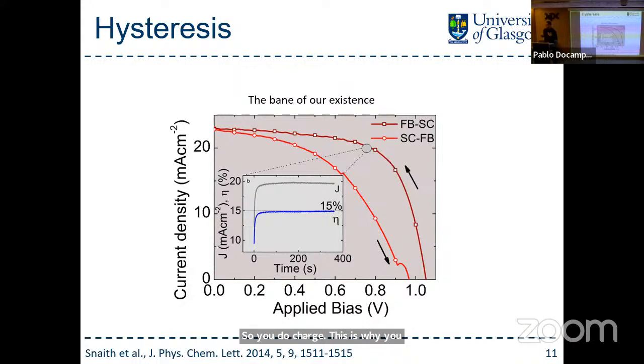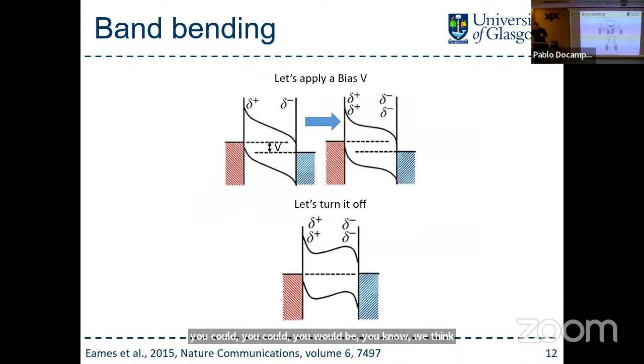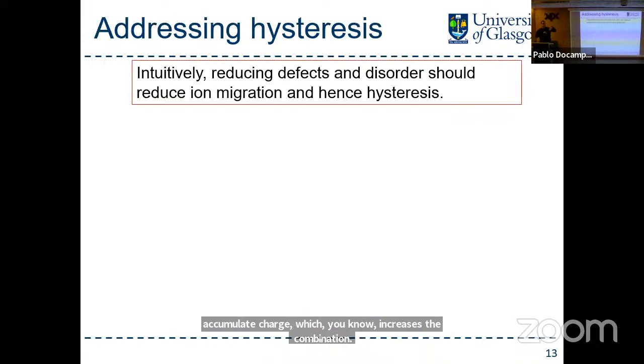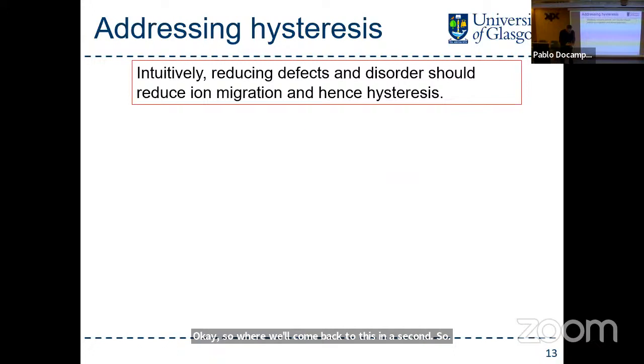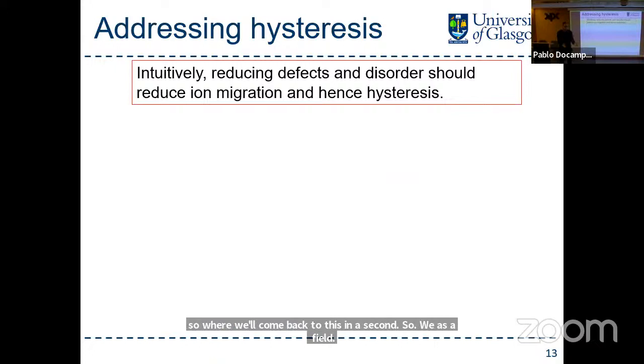So we think of them as not great. We don't want to have them. And this is a bit of explanation of what happened here. Basically, when we first applied the field, we moved the ions to the interfaces, which bends the bands. When we turn the field off, the ions remain in place. So now the bands bend, you get a dip in the conduction band, which accumulates charge carriers, which increases recombination. Don't worry, we'll come back to this in a second. So as a field, we thought, okay, ions are bad.